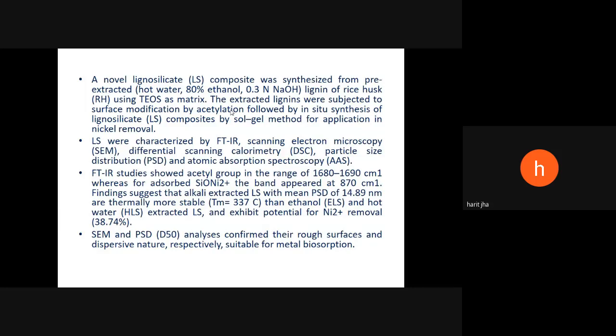So silica is also a byproduct, especially of the agro-base. This lignin silicate was then characterized by FTIR, scanning electron microscopy, differential scanning calorimetry, particle size distribution, and atomic absorption spectroscopy. The FTIR study showed an acetyl group in the range of 1680 to 1690, whereas for adsorbed silica nickel, the band appeared at 870 per centimeter.